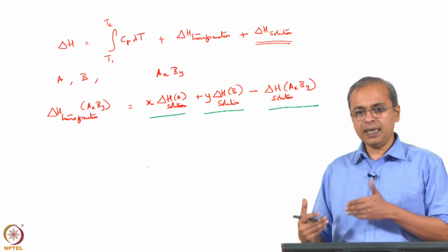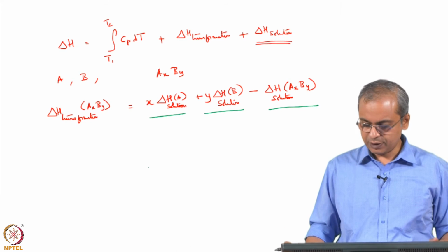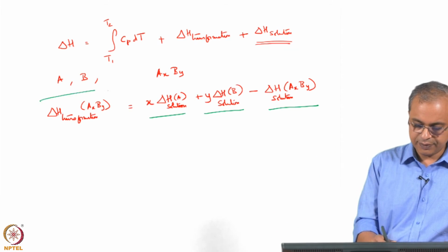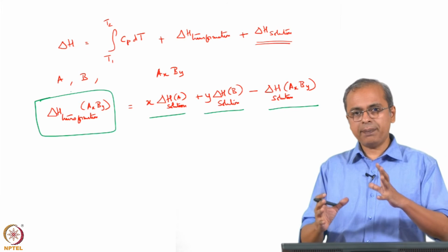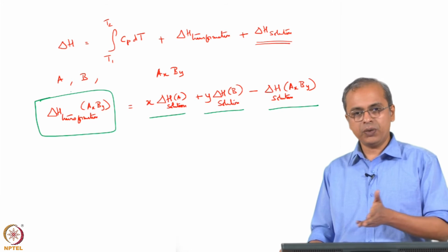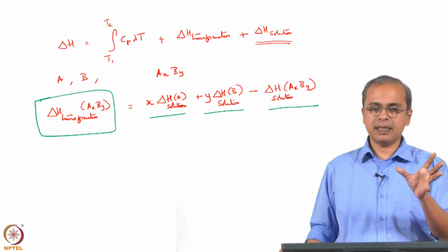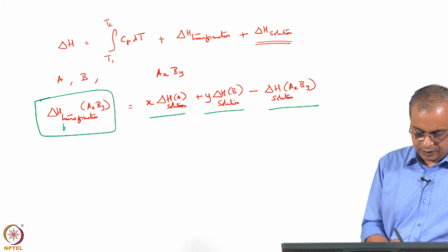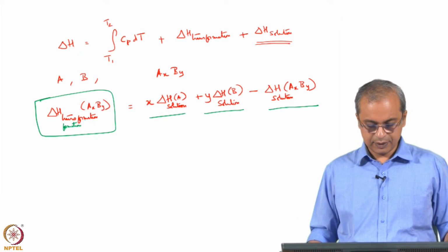Once you get these three pieces of data, for A, for B and for the alloy AxBy, you can put this information together and you get this transformation of AxBy. So, you can play around with these different pieces of information that you get from the calorimeter, do some calculation and arrive at the enthalpy of transformation, or formation in this case, for the AxBy system.